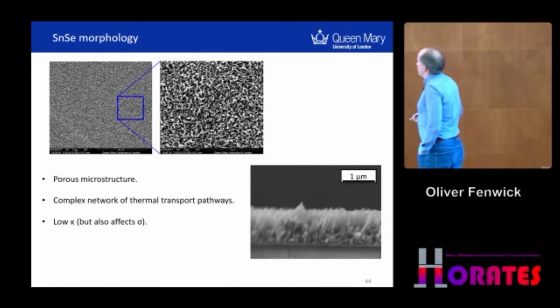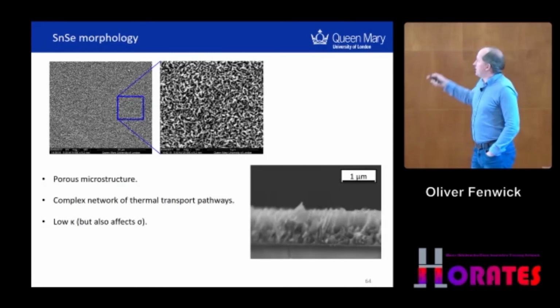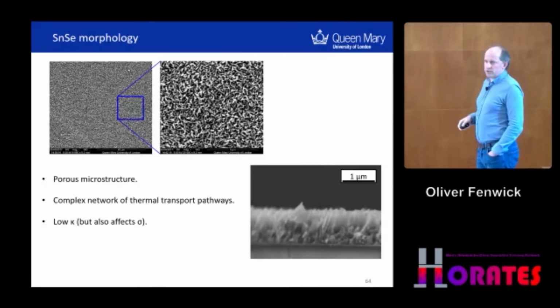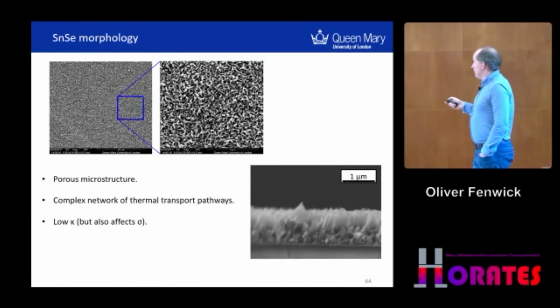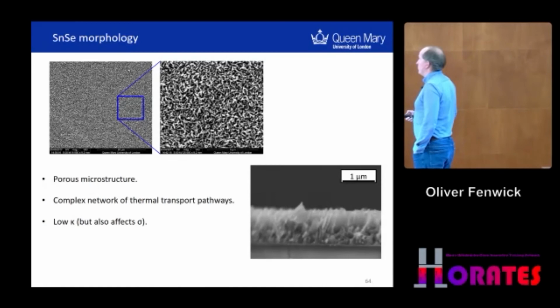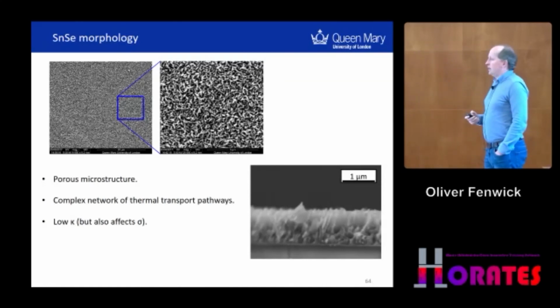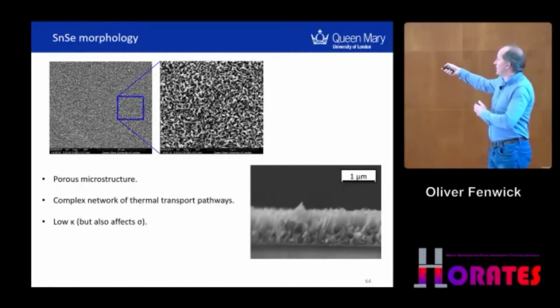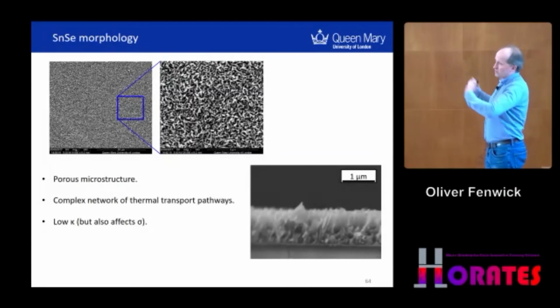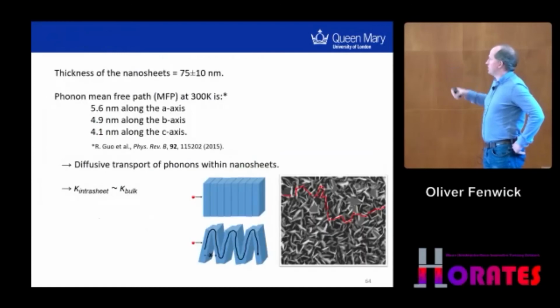If you think about thermal conductivity in plane, it looks like a network structure with holes in it. So it's a complex network of thermal transport pathways, equally, actually, a complex network of electronic transport pathways, which would explain why our electronic transport was also quite low compared with the literature.